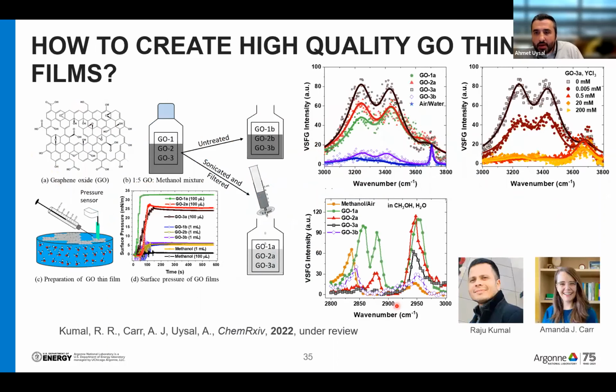Also, depending on your functional groups, as you change your graphene oxide, you might be creating a different film. So we need some universality in creating these thin films. And Amanda and Raju spent quite some time on this, and finally they developed a method to prepare these graphene oxide thin films in a very reproducible way by using very little amounts of graphene oxide, minimizing the graphene oxide dissolution in water. And this basically includes some sonication in methanol and then filtration.